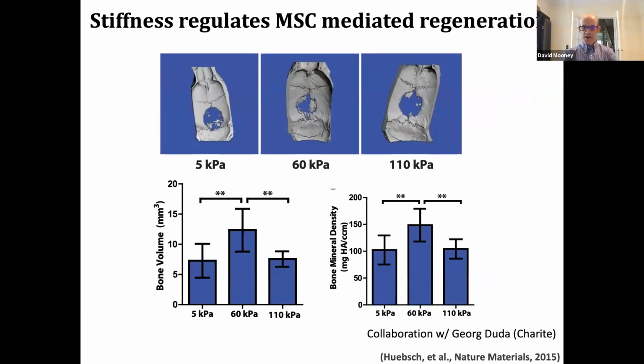So this was a documentation that the mechanical properties really did matter in a 3D context and could control stem cell fate. Now, Nate went on in a subsequent paper and demonstrated that he could indeed control not just the fate of the cells outside the body, but actually bone regeneration in the body by solely manipulating the stiffness of these gels. And this is the first demonstration that stem cell mediated regeneration could be regulated by these types of physical cues in the body. And he took a small number of stem cells, he put it into a cranial defect in the skull. And the idea was not to completely regenerate the bone, but to use a small enough cell number that we could see what impact the mechanics made. And you can appreciate that when he transplanted the cells in gels that were of the right modulus, he got the most significant bone regeneration, for example, as indicated by the bone volume that resulted. So both in vitro and in vivo, he found that the mechanical properties really regulated the ability of stem cells to differentiate and regenerate tissues.